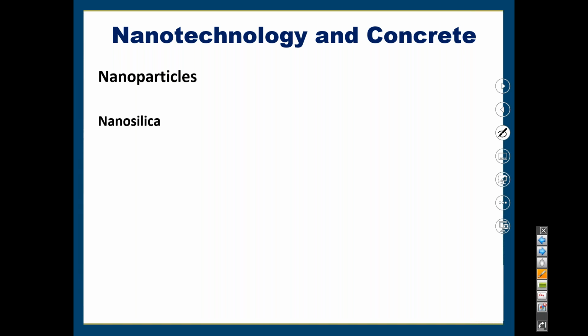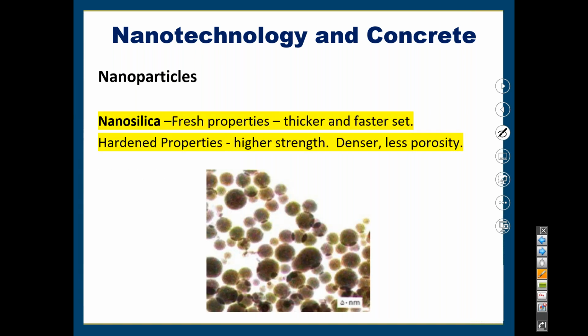So nanoparticles, some of the nanoparticles that have been developed or are being developed are nanosilica, nanotitanium dioxide, nanocalcium carbonate, and nanosized cement. I'll talk about each of these just briefly, but nanosilica, which is probably the most widely used nano material, it can come in two forms. It can come in a powder form, or it can come as a colloidal silica, which is most common, and that's usually in a liquid, so it's kind of added like an admixture.